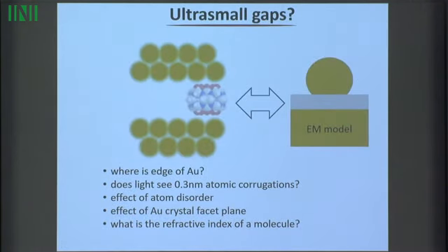So then we start to worry, well, actually, of course, my gold is made of atoms. This is a simulation that I might do electromagnetically, and this is just a vague picture. So where is the edge of my gold atoms in this simulation? I told you this is 0.9 nanometers, and that's because when I solve my electromagnetics model, I get a fit to the data, which is very, very clean, when I make the gap 0.9 nanometers. That does not mean the gap is 0.9 nanometers. What would I mean here?